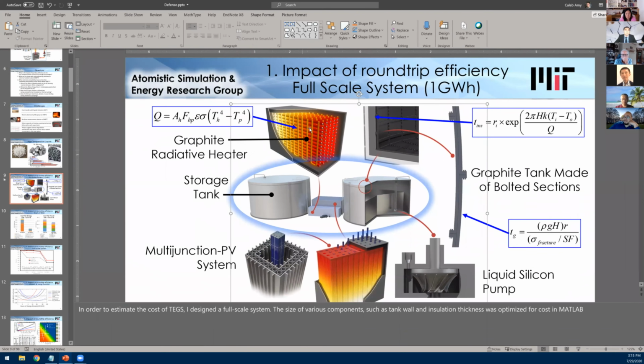Okay, so this heater section shown here has a lot of these horizontal pipes. What we were considering was a 10 millimeter inner diameter, 20 millimeter outer diameter. So this is a 5 millimeter wall thickness. And that's an interesting question, because if you have a dissolving issue, you might make the wall thicker to resolve it.